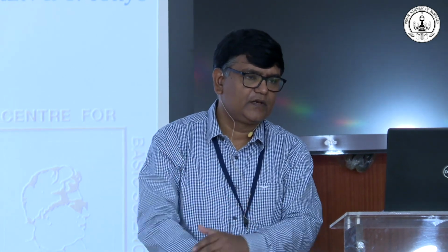Does the demagnetization depend on the thickness in any way? Yes, the demagnetizing field depends on the thickness. And also the time scale. And there is a perpendicular magnetic anisotropy at the interface of cobalt and platinum due to the d-d band hybridization. So there is a substrate effect also. Substrate effect is there, but here, because it's a big stack, the strain effect is relieved. Relieved at nanometer thickness? Yes, within few layers it is relieved. There is very little strain, and that is relieved within few nanometers. Okay.